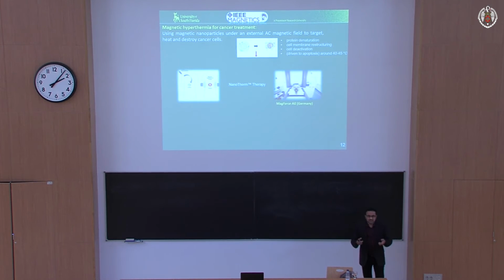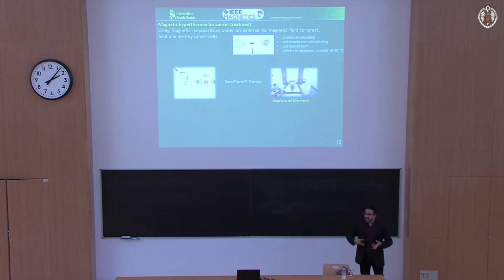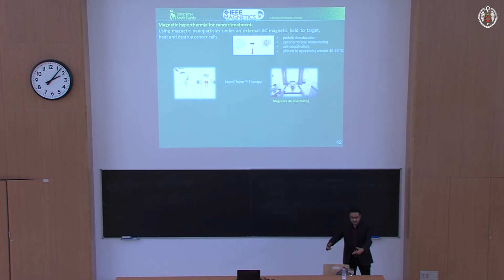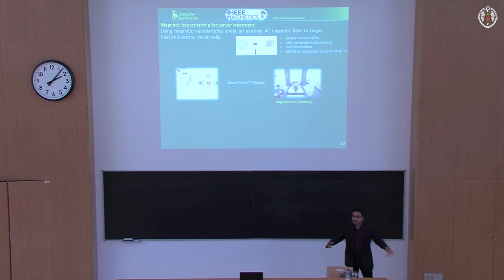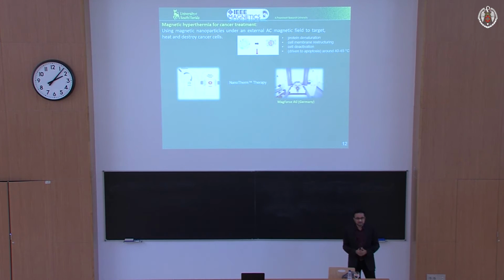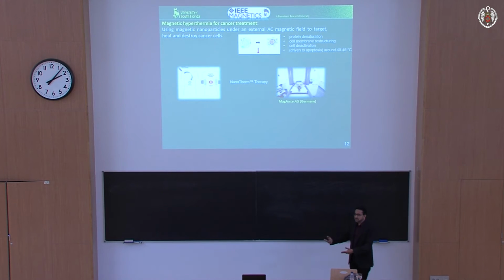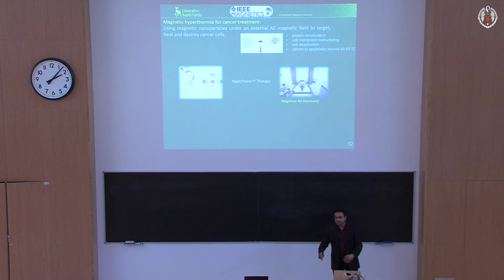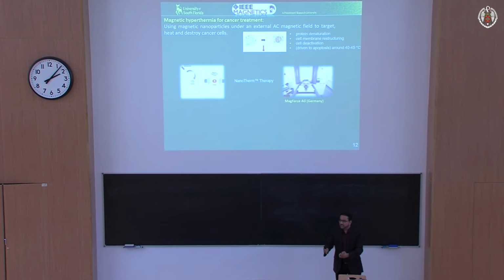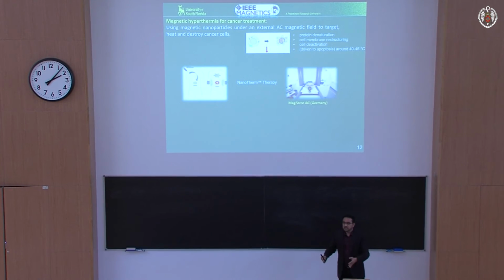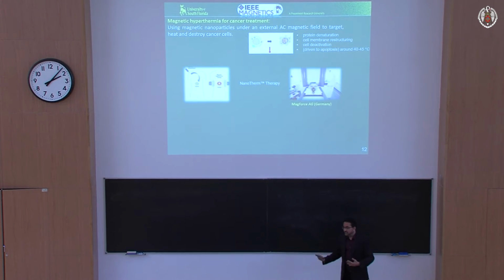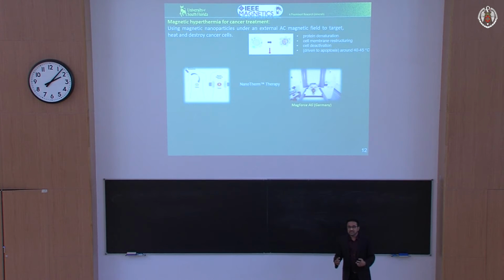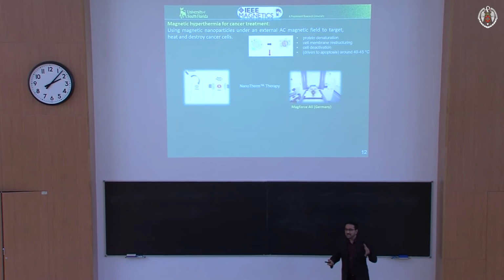So the goal here is to use magnetic hyperthermia, which is relatively benign, as a supplemental therapy in addition to chemo, of course, so that you can actually reduce the dosage of chemo. People ask me all the time, is hyperthermia going to replace chemotherapy? No, the answer is no. Chemo is still the most effective way of treating cancer. However, we believe that magnetic hyperthermia, which I'm talking about, is going to be an excellent supplemental technique that will add on, and in fact it can reduce the chemo dosage, it can increase the time between chemo dosages, and it can improve the quality of life of the patient quite a bit.